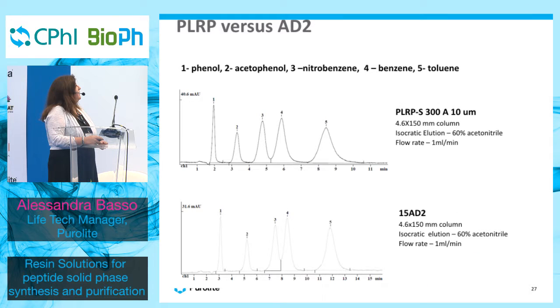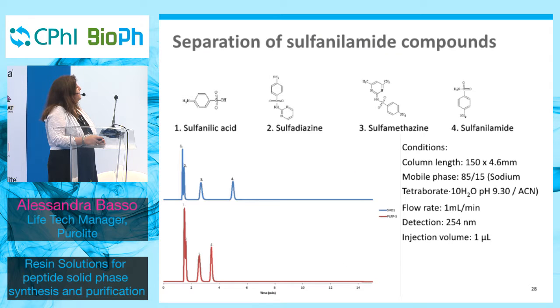Again, here is a comparison with other aromatic compounds, so PLRP versus the AD2 material, and we have a very similar profile in both materials. Again, here we compare the 10 microns, so better resolution, with the 15 micron with larger particle size. Here there are other molecules, sulfanilamide compounds, and again we compare a 5 micron with another material on the market, and you see that our material has a little bit different selectivity, so you have a better separation with the blue line.